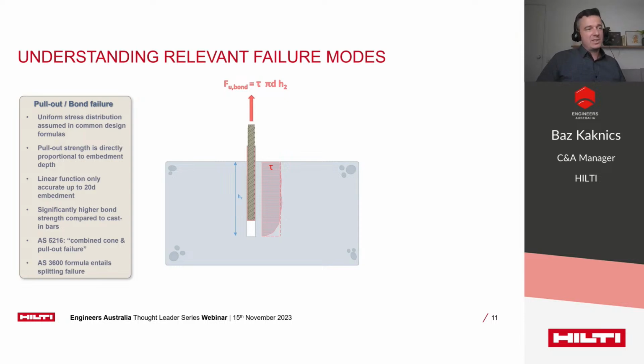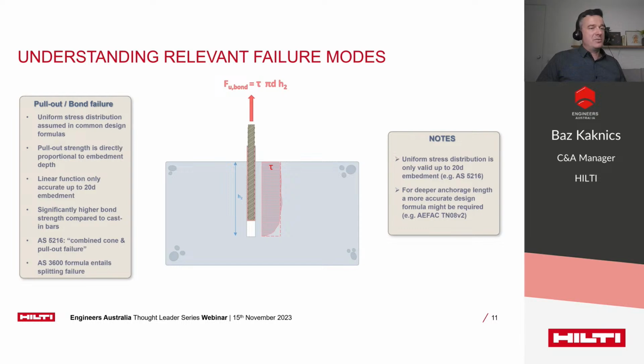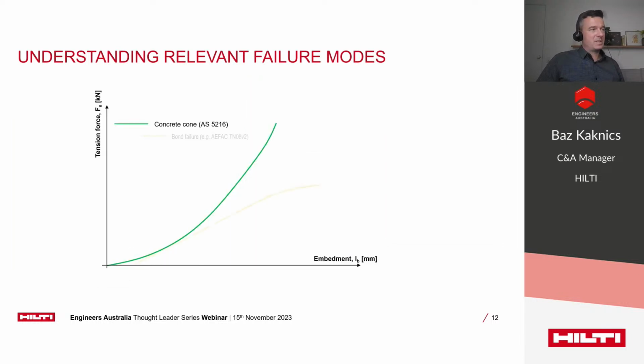AS3600, on the other hand, for the design of cast-in bars, is combining the pull-out with a potential splitting failure, which could limit the development of the full bond strength in case there is not adequate concrete cover surrounding the bars. Regardless of the different approaches in the various design standards, the basic principles of bond failure are still valid here, and an important takeaway is that the uniform stress distribution only holds true up to an embedment depth of 20D. This fact again might necessitate a different design approach for post-installed rebars versus anchors.